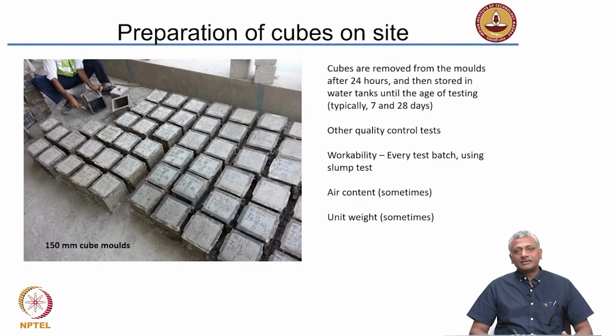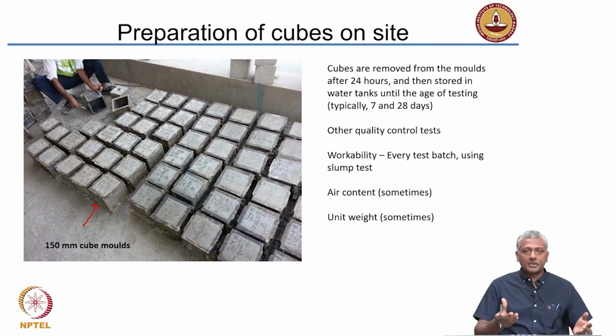Now on the job site, as I said, there has to be some quality control done to ensure that the concrete that is supplied is meeting the demands of what the design has been done for. Okay. As I said, one of the common tests that is done on the job site is the slump test to determine the workability. But apart from the slump test, you also need to ensure that you determine the strength somehow. And for that purpose, when the concrete is supplied to the job site, you prepare these specimens, 150 millimeter cube specimens. At least in India, we use cube specimens to determine the strength of the concrete after a certain period of time. So you have the concrete truck that reaches the job site, you do the slump test, then you take material to prepare these cubes. Okay. So you prepare the 150 millimeter cubes.